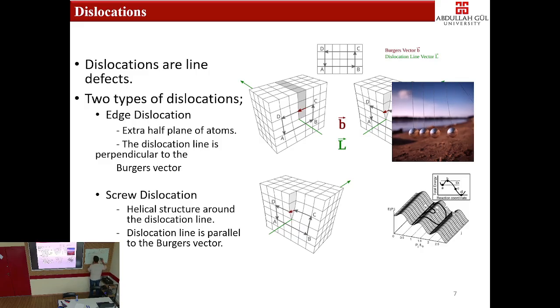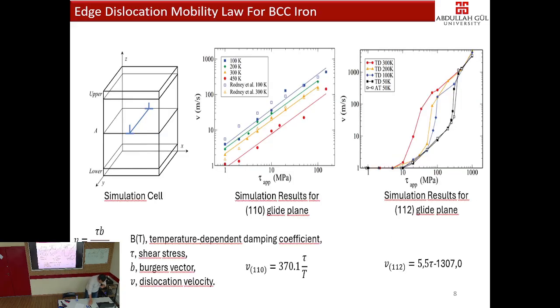For BCC, the Burgers vector is always 1-1-1. Do you know which slip planes we have for BCC? We have 1-1-0, 2-1-1, and 3-2-1. In total, 48. Even though we have more slip systems in BCC, including pencil glide and everything, FCC is way more ductile than BCC due to the fact that one is deforming with edge dislocation and the other with screw dislocation. All right, so what we have done in this research.